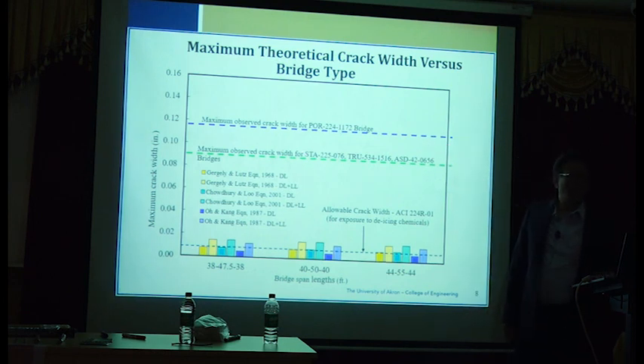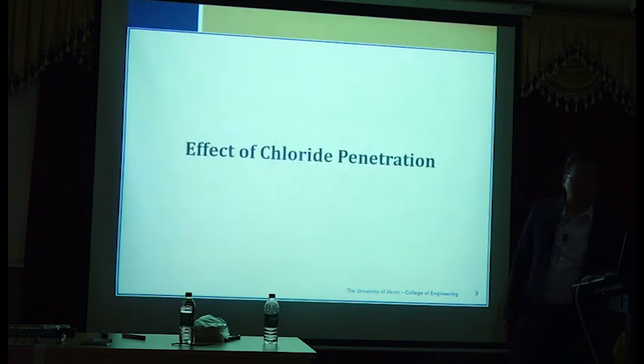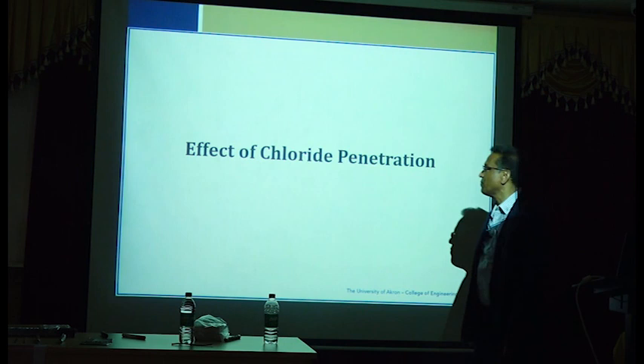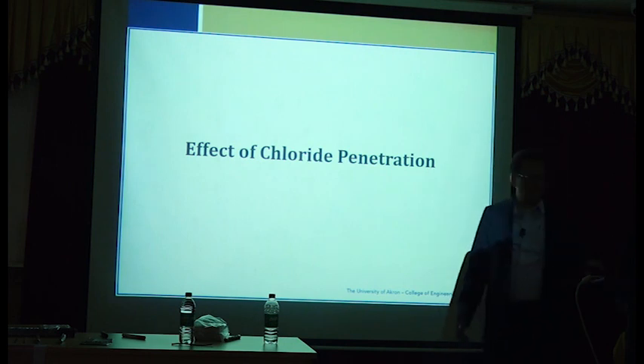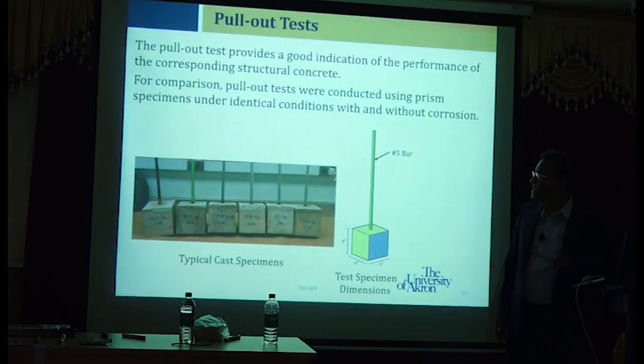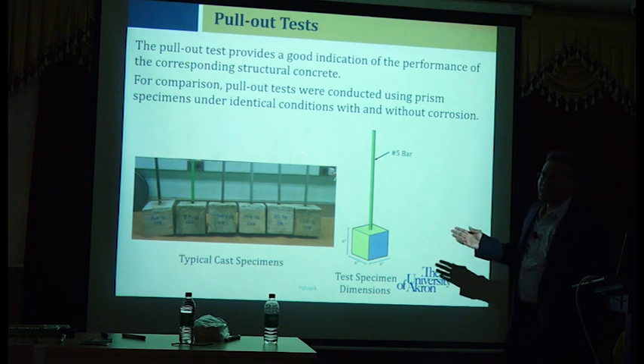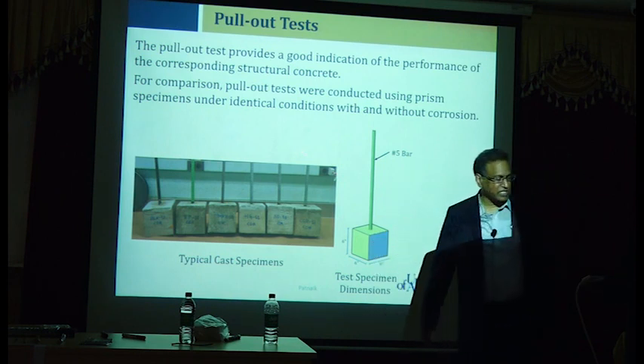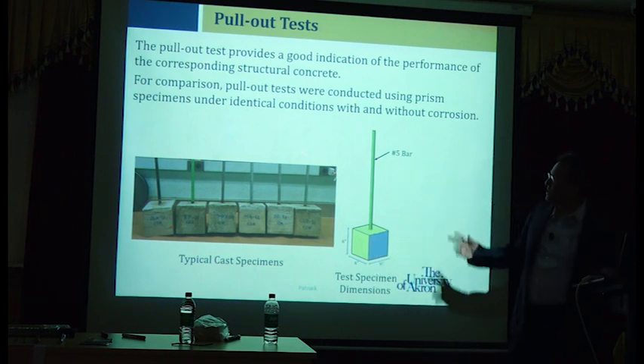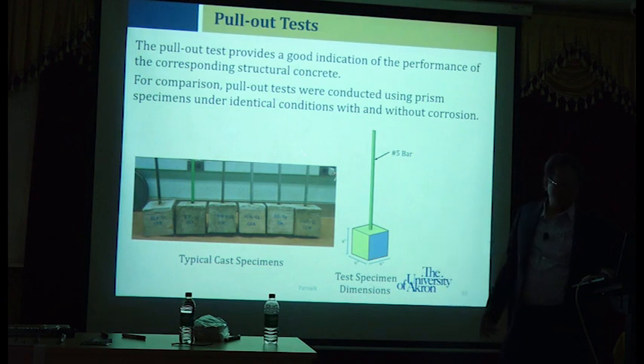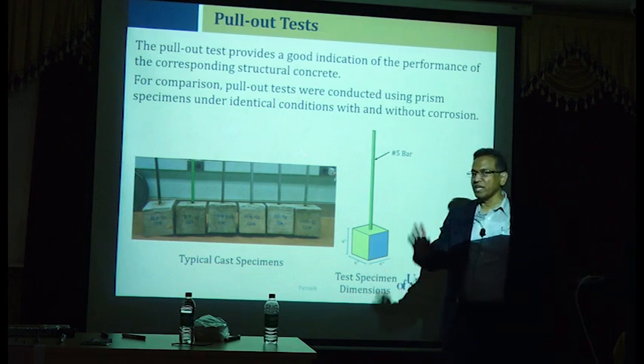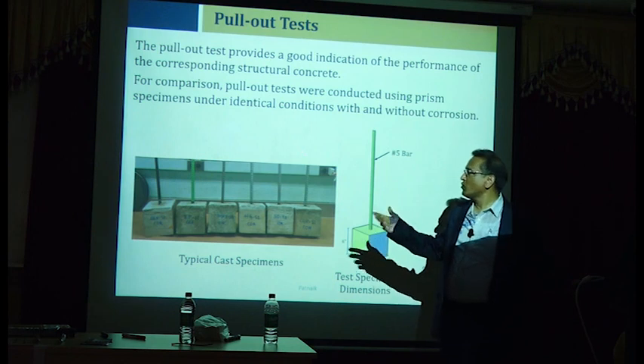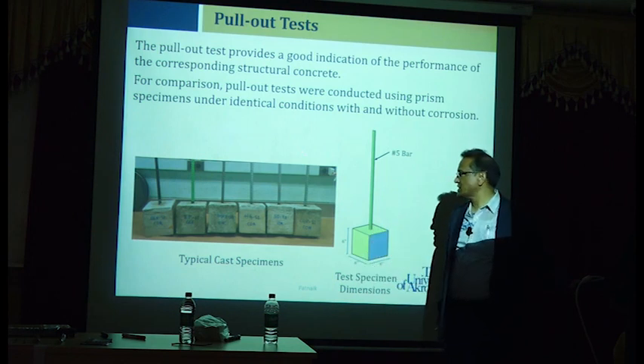So with that understanding, we said, what is the effect of cracking? That's the first thing we started to look at. So what's the effect of chloride penetration into the cracks? So we did a lot of accelerated tests and very simple pull-out tests. This is not even a standard these days. ASTM no longer considers this pull-out test with blocks of concrete as standard. That's gone. But we still wanted to do these tests.